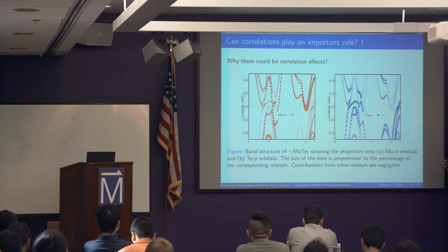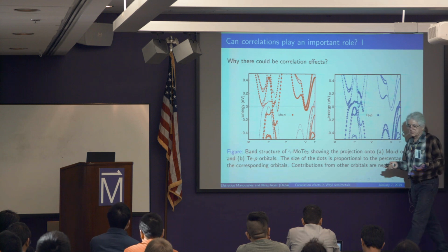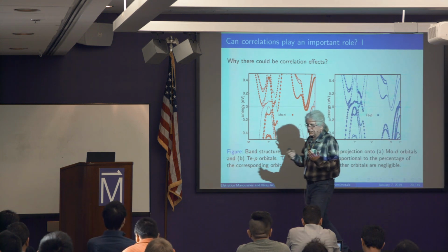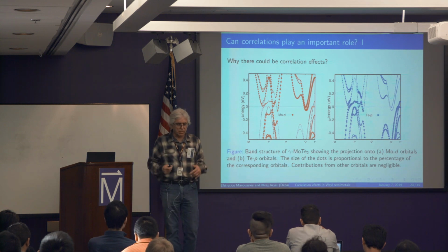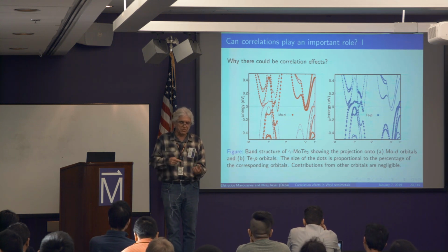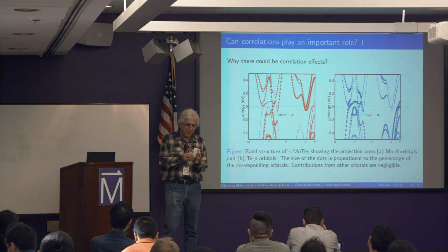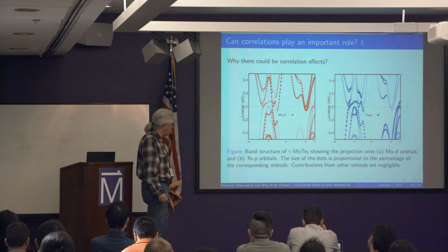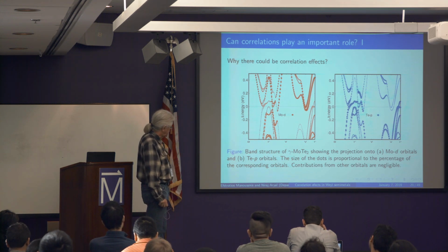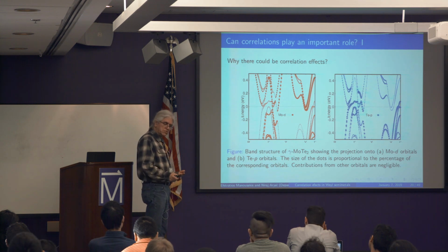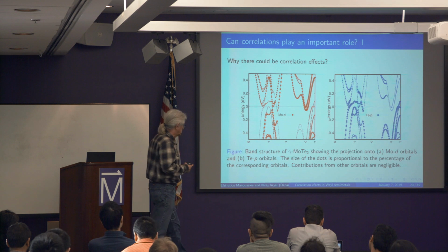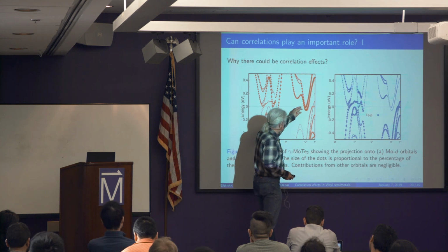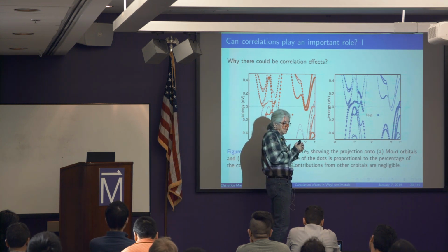And so why am I doing this decomposition? Because I know from my experience that the D orbitals are more localized, and so when you put two electrons of opposite spin on a D orbital, they will feel this strong Coulomb repulsion. So one, in this case, needs to implement this U in the GGA calculation, because every time you put electrons into this D state, they will feel more repulsion.